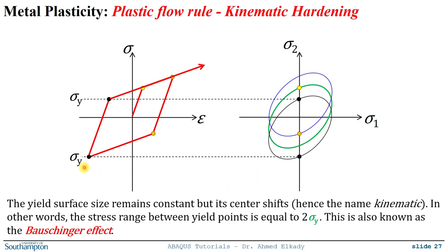In other words, you can say that the stress range between the yield points, so if I measure the distance between this yield point in, let's say, compression, and this yield point in tension, this range is equal to 2 sigma y, so it remains constant. So this is what we call kinematic hardening, and this is also known as the Bauschinger effect. So you have this asymmetric hysteresis. If you keep pushing further, you will see that you start yielding much, much earlier, not in a symmetric way, as we have seen previously in the isotropic hardening.